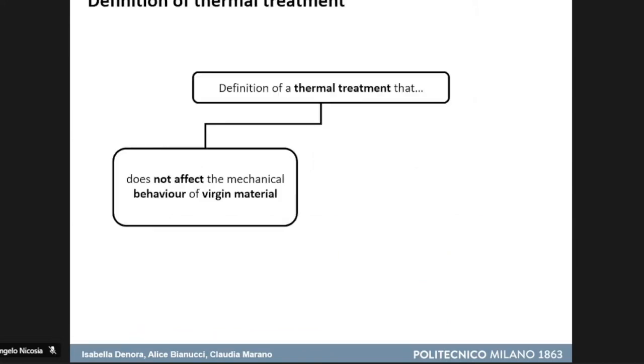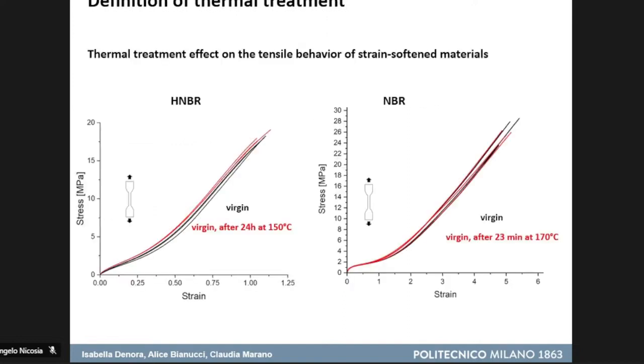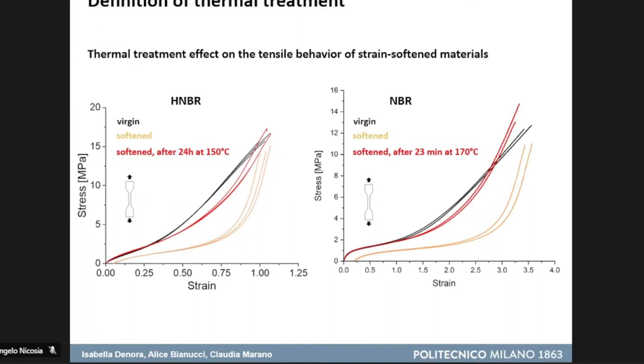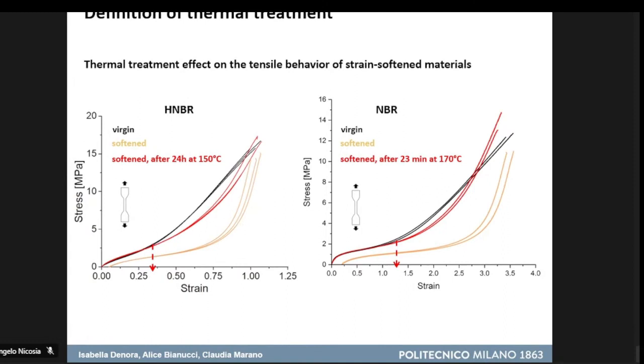But how have we chosen this thermal treatment? We have chosen a treatment that could recover the mechanical behavior of virgin material. We have performed this type of test, uniaxial tensile test, and here I've reported the curves of the virgin material, of the softened material, and of the softened material after the thermal treatment. We can see that a good recovery was observed, especially at lower deformations that actually were higher than the deformation experienced during the fracture test. So a good recovery was obtained for both the materials.